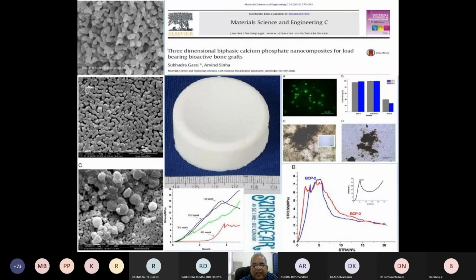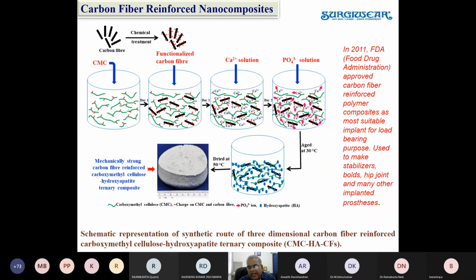That was the hydroxyapatite. We did a similar thing with the biphasic material and developed a load-bearing biphasic nanocomposite in a biomimetic way. This process was also taken by Surgiwear for commercial exploitation. We confirmed the bioactivity again through interaction with Shri Chitra Tirunal, Trivandrum. Whatever we were doing, we were getting the bone graft with higher mechanical strength as well as good